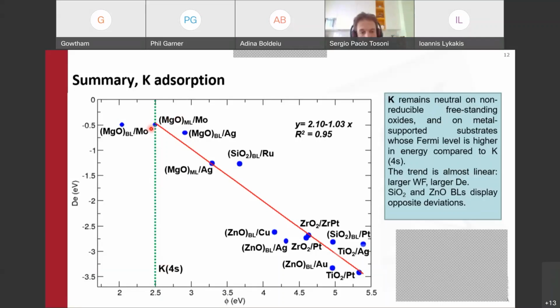As soon as the work function becomes large enough to make the charge transfer favorable, the binding energy of potassium in the form of cation starts to increase. And in spite of the fact that many other factors actually matter, like the thickness of the film, the morphology, and so on, the correlation is really quite good. So in a way, potassium really obeys a strictly ionic rule of bonding on oxide thin films. And the larger the work function, the larger the adsorption energy.